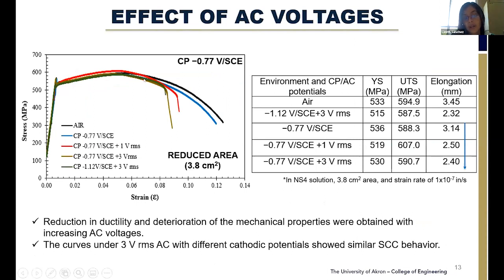So here, basically, we see how the sample with only cathodic potential, the blue one, shows a good elongation compared with the other samples. However, when AC voltage, 1 volt and 3 volts, is applied, the elongation decreases. The mechanical properties of the material are decreasing due to the AC voltage that we are applying. Basically, the yield stress and the maximum stress of the sample are similar, and the elastic part overlaps, but the elongation is decreasing with higher AC voltage.